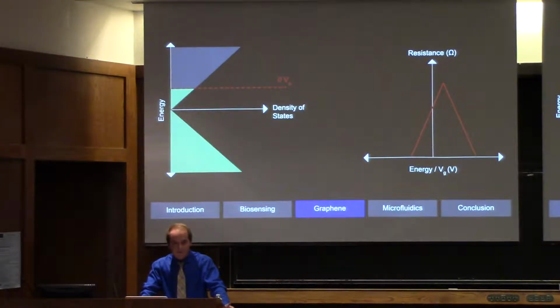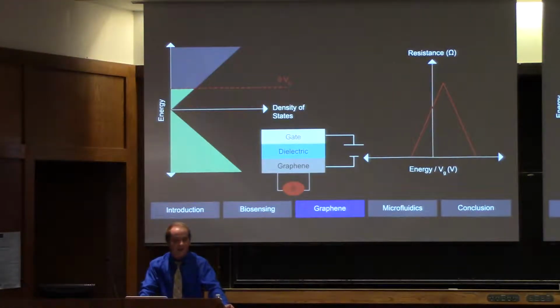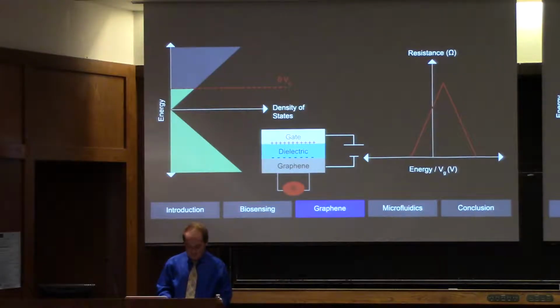Using what's called a gate voltage, we can actually control the charge on the graphene in order to return the graphene to its Dirac point, basically turn it to the place where it's charge neutral. We do this by creating a voltage difference between the graphene and a gate, with a dielectric in the middle. This basically creates a capacitor, which allows charges to build up on the graphene. And using a simple DC power source, we can control the charge on the graphene at any time.